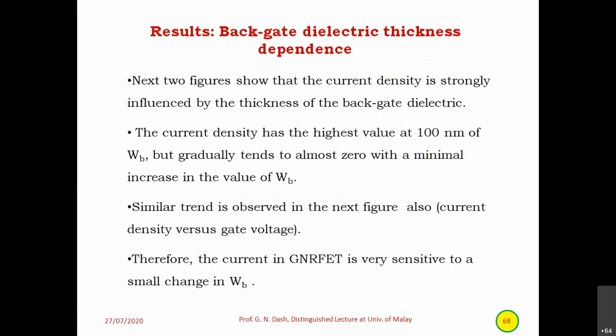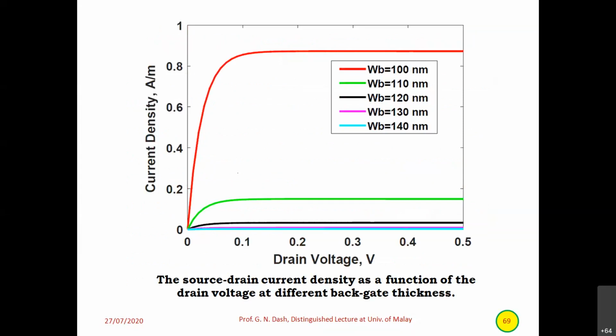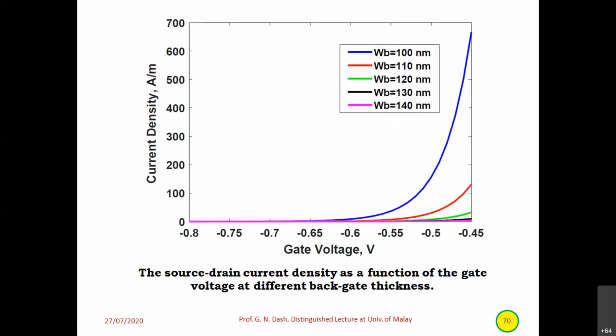Results: backgate dielectric thickness dependence. Backgate dielectric, that means WB. There are two figures for that. Again, drain voltage versus current density. The next two figures show that the current density is strongly influenced by the thickness of the back dielectric. The trend is similar here. The current is very sensitive to small WB. As WB increases, the saturation current decreases, and drastically at about 140 nanometer it almost becomes zero. Here also WB increases, current decreases. Same trend.